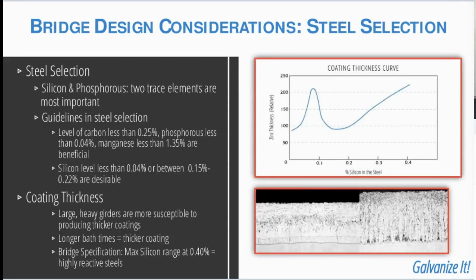The next topic to consider and discuss is with respect to steel selection. There are recommended ranges for elements in the steel, such as silicon, phosphorus, carbon, and also manganese, which provide a galvanized coating of typical thickness and also typical appearance. Steels that are going to be outside of these ranges are known as reactive steels. They might have a thicker coating or a rougher coating, but they're often acceptable.